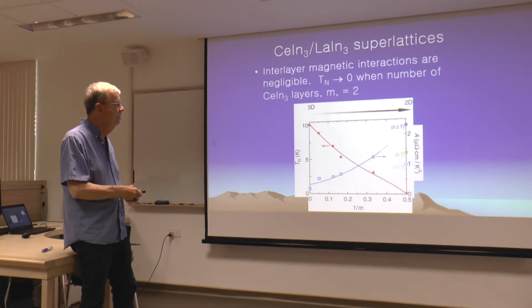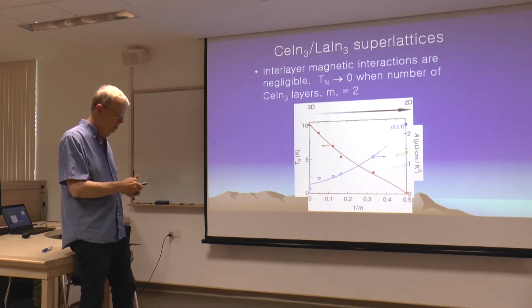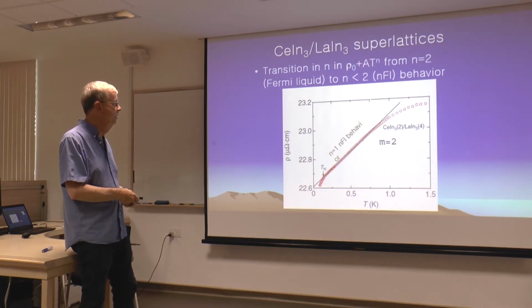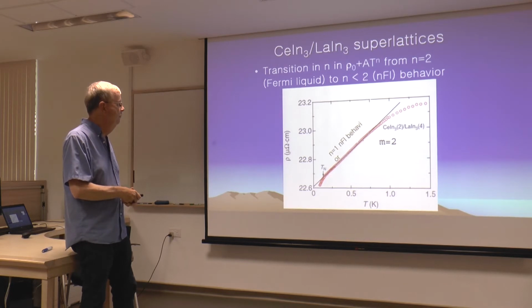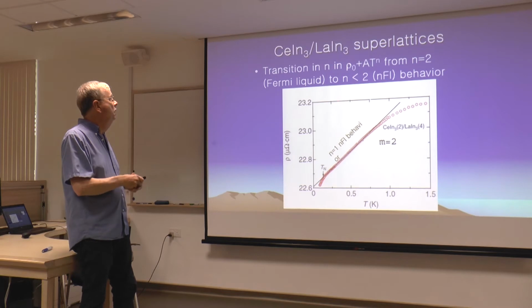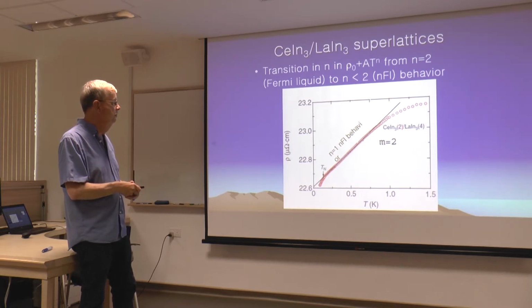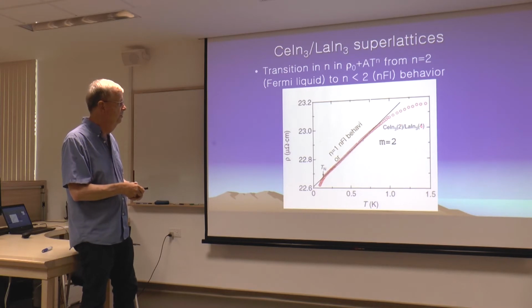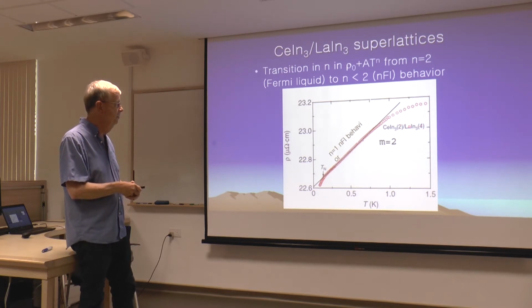As I move across by tuning, at low temperature, I can get T squared in the resistivity, and now I'll finally slow down and look at it. So here I have m equal 2, yep, here's m equal 2, and I have 4 interspacing layers of lanthanum instead of 3.